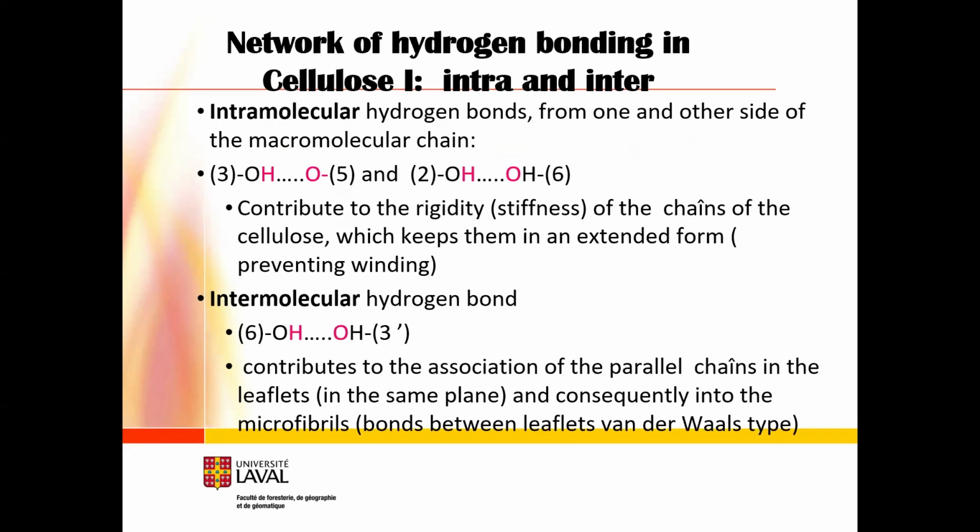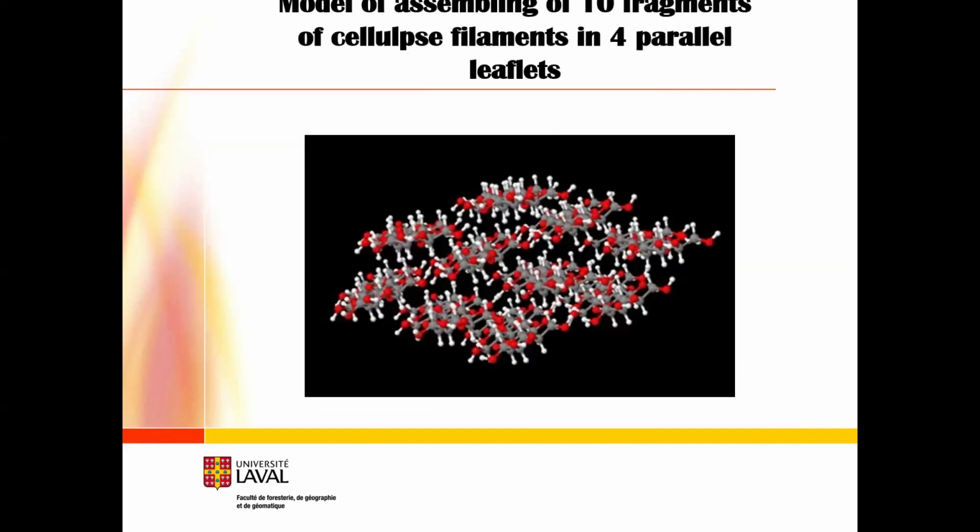hydrogen bond. What is important here to note is that the cellulose is actually in its native state, which we indicate as cellulose 1. It is organized in sheets, and the hydrogen bonding between the parallel chains is only in the sheets. And the sheets are united only by lower energy intermolecular interactions of the van der Waals type, which keeps them all together.